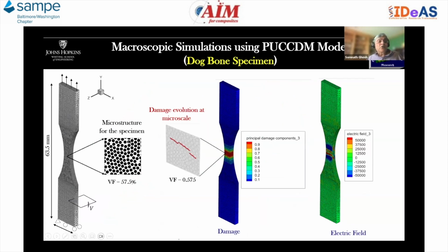With that, corresponding to each microstructure, we can then have a pure macroscopic evolution. Here we are showing the evolution at the macro scale associated with the damage evolution. That means this is the evolution of cracks in the microstructure, and this corresponds to the evolution of the principal damage components in the macrostructure, as well as the evolution of the electrical field.